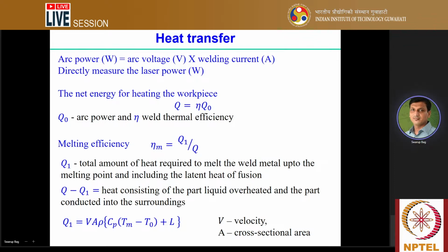So therefore, if we take care of this part, then we can introduce the efficiency term. The net energy for heating the workpiece, once we create the arc, is the effective energy transferred to the workpiece. That is where we introduce Q equal to efficiency times Q0. Q0 is the actual arc power, and eta indicates the weld thermal efficiency. So that's the factor we have considered here, the weld thermal efficiency, that indicates the actual amount of heat transferred to the workpiece.